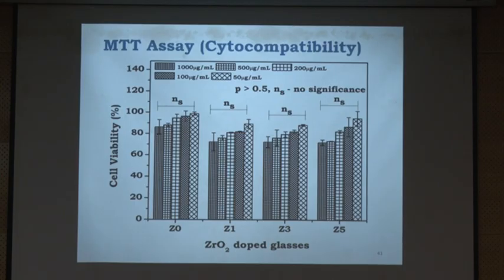If you see this bar graph, Z0 is without zirconium, the base material. Z1 is 1%, Z3 is 3%, Z5 is 5% of zirconium. And if you see the graphs, all the bars have cell viability above 70%. The first one is the control, the other 4 are with different compositions. The first is slightly 80 and above. The second is 70 and above, the third also 70 and above, the last one also above 70.